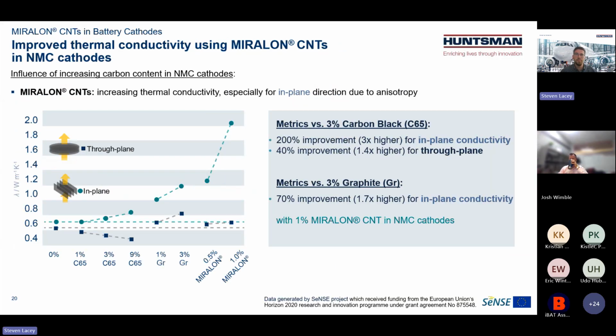Now, from a thermal conductivity perspective, this is very interesting, and a lot of people don't report this. So if you think about it, especially in larger cell formats, when you have a very good thermal conductor, you can mitigate and remove the heat towards the current collector more readily. And this buildup of heat, especially when you're going at high rates, could be an issue if you do not have such a good thermal conductor. So in this case, we also compared directly to carbon black as well as graphite to our MIRALON carbon nanotubes. And we can see that also because of this anisotropy,